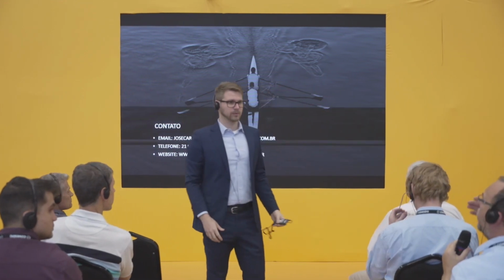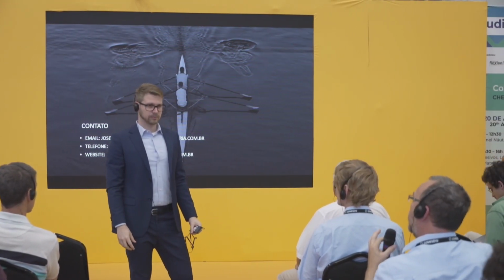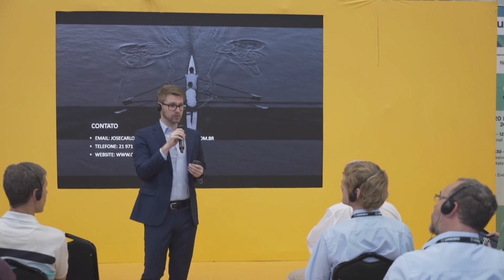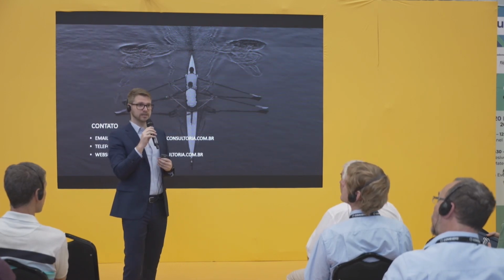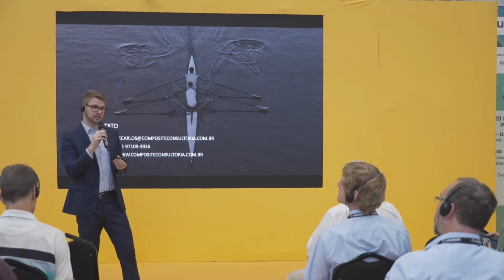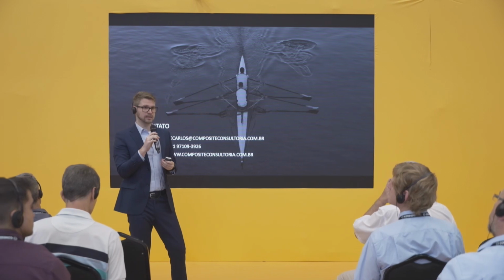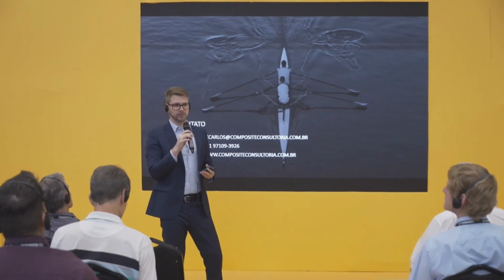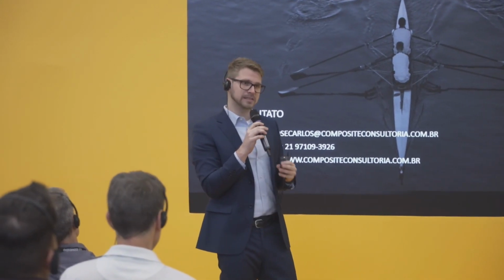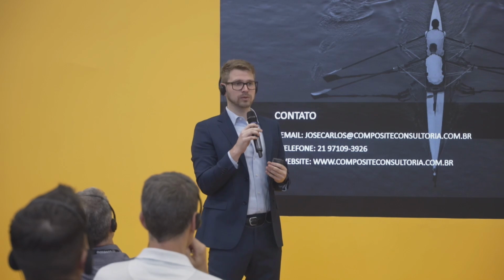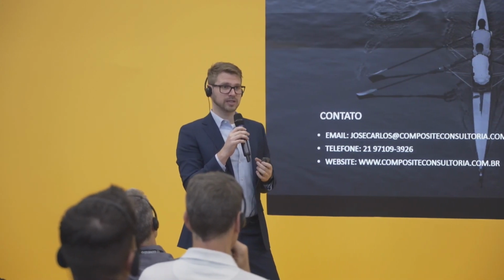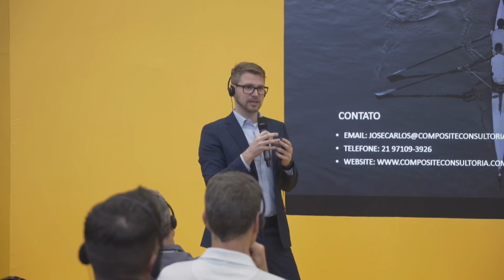Any other question? When you put a lot of screens together, how do you put them together? Are they sewn? The adhesive, contact adhesive, usually Super 77 3M. It's an inert adhesive for this type of resin. And for sure, you should use the least as possible, only enough to keep it in place. When we place too much glue, we can create points where the resin will not penetrate.